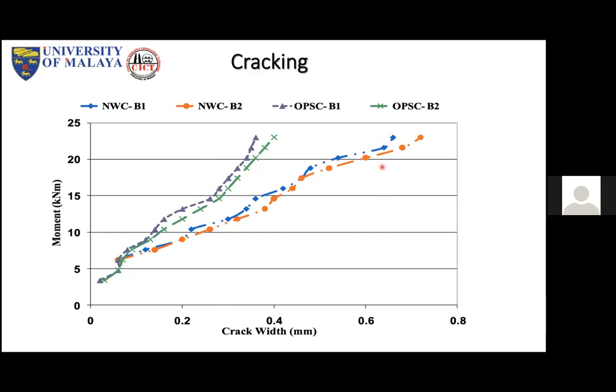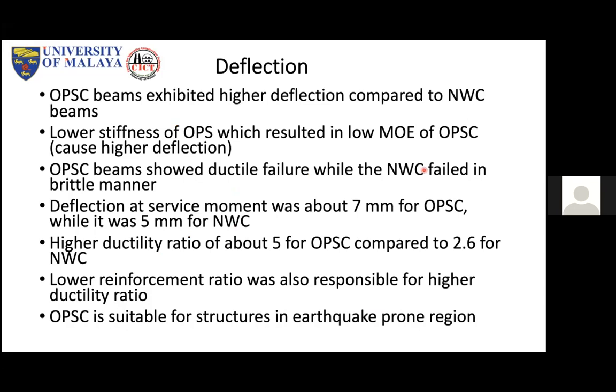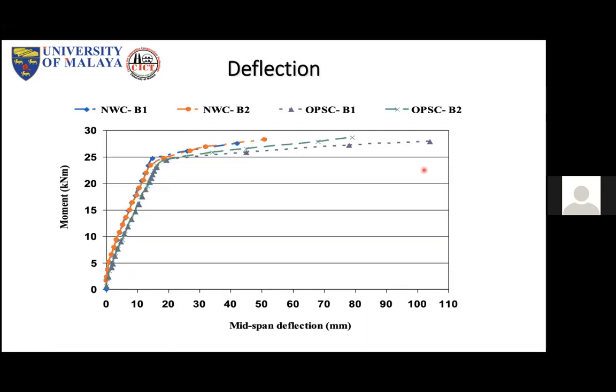But this one, because of the ductility, it can extend. This one I don't have time to explain. However, from the graph, we can see the lightweight concrete beams that were using the oil palm shell as the coarse aggregate. We can see the deflection even up to 80 or 100 mm. But here only 40 to 50 mm, because this is not ductile, whereas this is ductile.